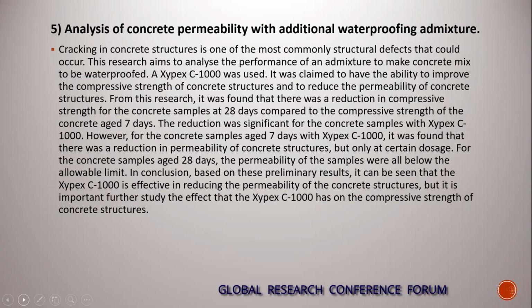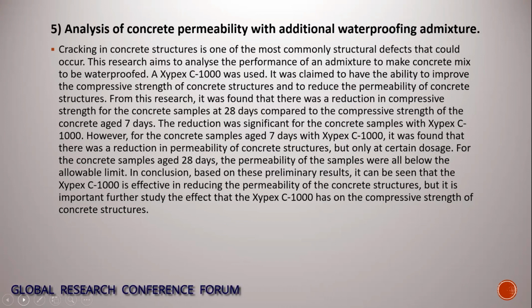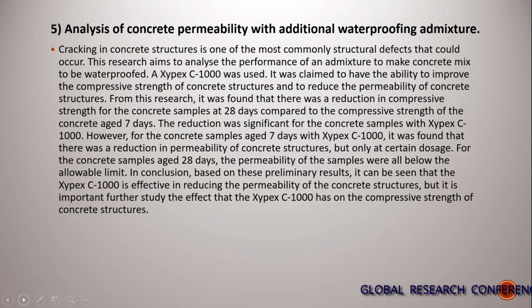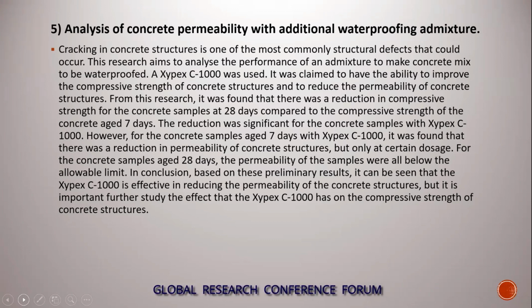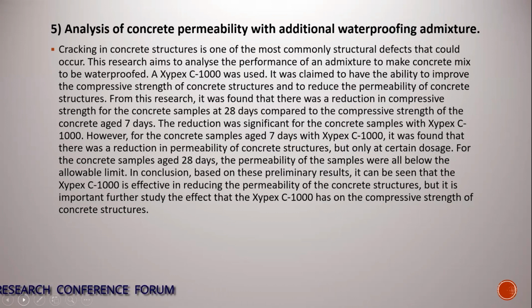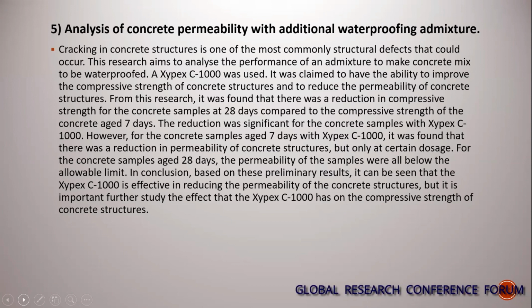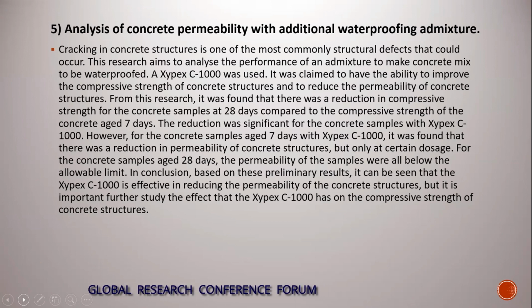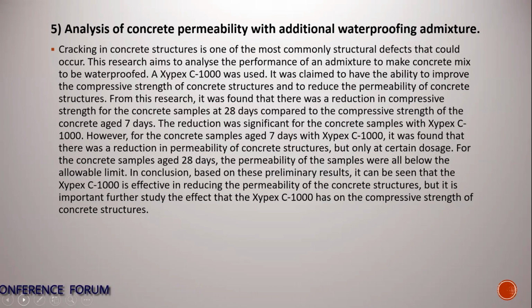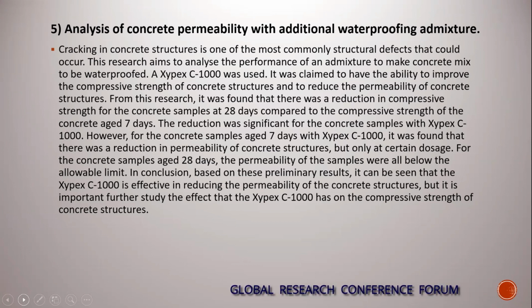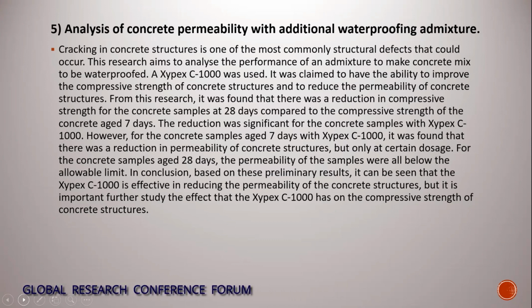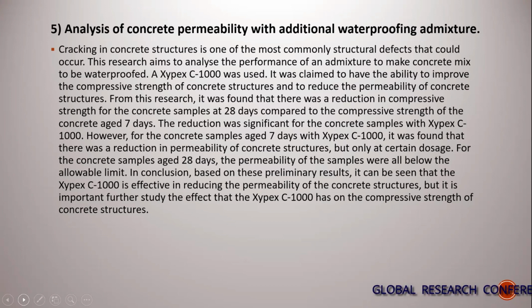From the research, it was found that there was a reduction in compressive strength for the concrete sample at 28 days compared to the compressive strength of the concrete aged 7 days. The reduction was significant for the concrete sample with C1000. However, for the concrete sample aged 7 days with C1000, it was found that there was a reduction in permeability of the concrete structure, but only at certain dosage. For the concrete sample aged 28 days, the permeability of the samples was all below the allowed limit.